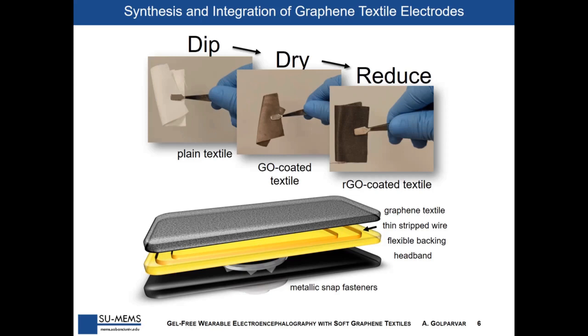After the reduction, the textile was washed by immersing it into deionized water to remove any unbound chemical residues from the fiber surface, and only stable and well adhered reduced graphene oxide forms remain on the textile. As you can see, during the conversion of graphene oxide to reduced graphene oxide, there was a noticeable change in the textile color from brown to black. This is due to the removal, of course, of oxygen containing groups.